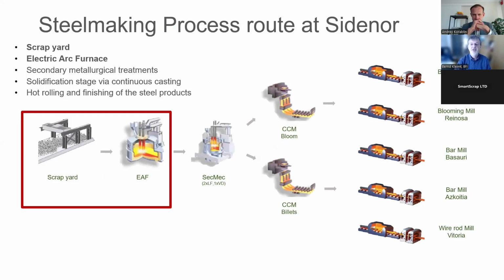So first of all, the steelmaking process route at Sidenor in Spain. So here the steel is produced completely from scrap, which is sorted at a scrapyard and then charged into the electric arc furnace. They have a very sophisticated secondary metallurgy treatment with 2 ladle furnaces and 1 vacuum degassing plant and 2 different continuous casting plants for blooms and billets and 5 different rolling mills in different plants in the northern part of Spain.